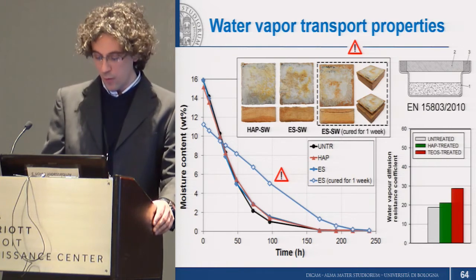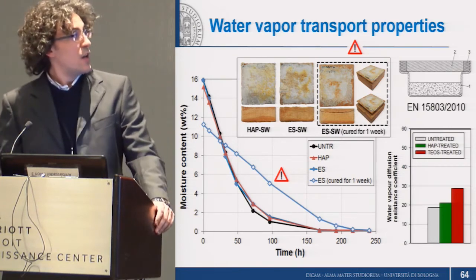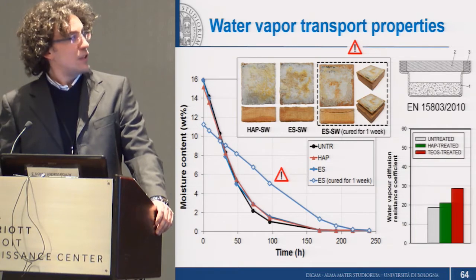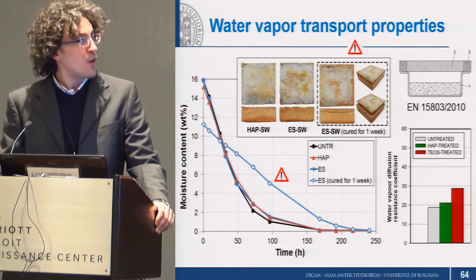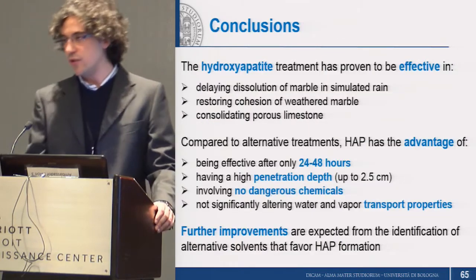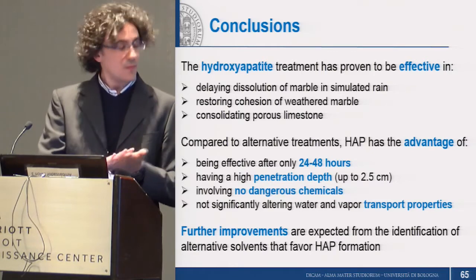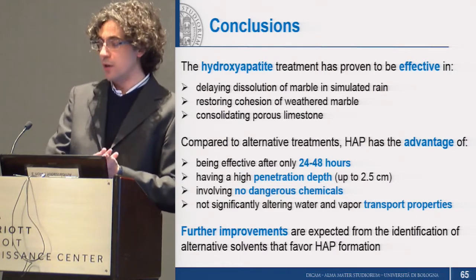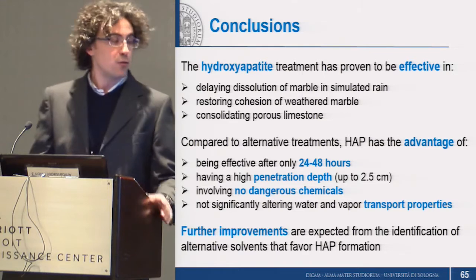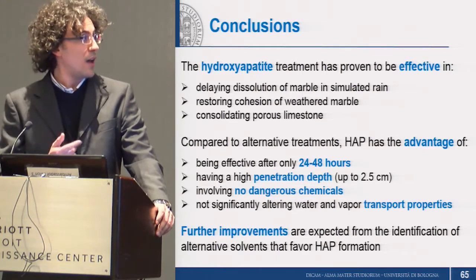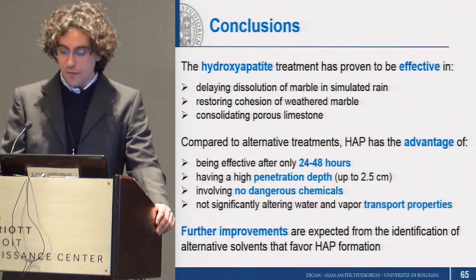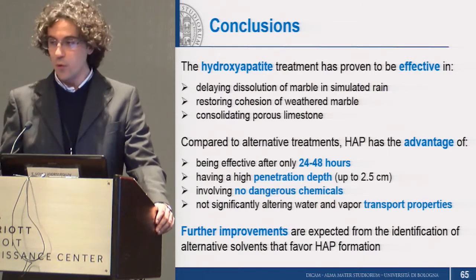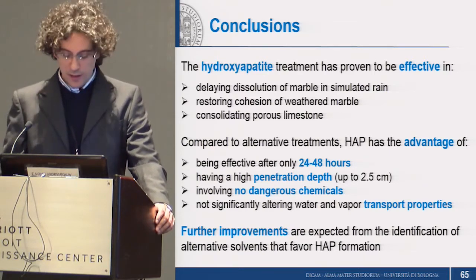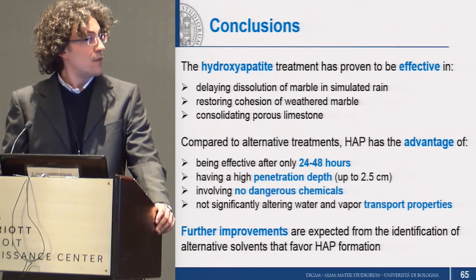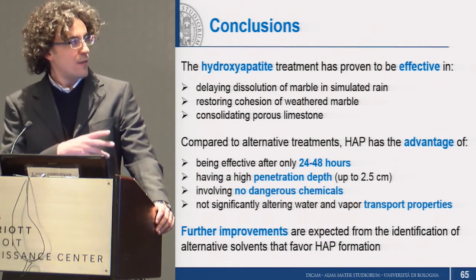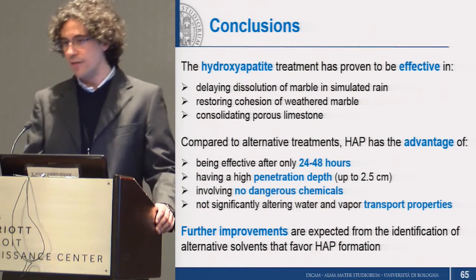This is not the case of our treatment, so this is another positive feature of this phosphate-based consolidant. So summarizing, our hydroxyapatite treatment was able to significantly prevent marble dissolution and to provide a good consolidating ability for marble and for limestone. We are confident to be able to further improve the performance by screening alternative solvents. And anyways, our treatment has several advantages over the commercially available ones.